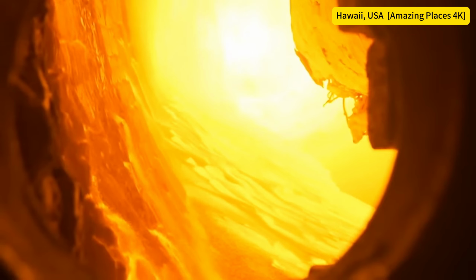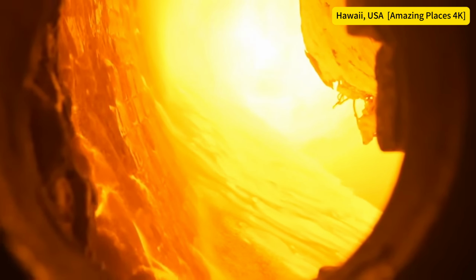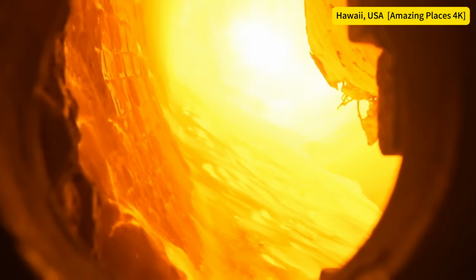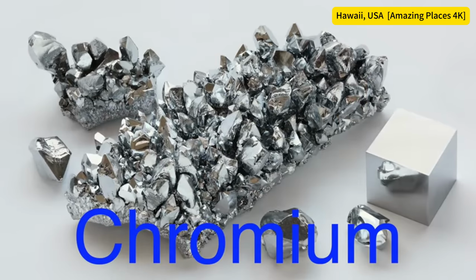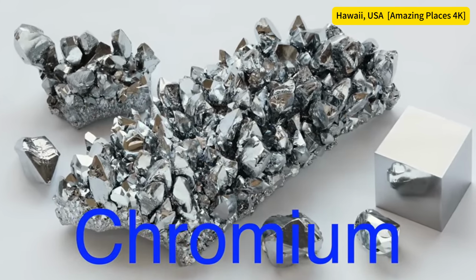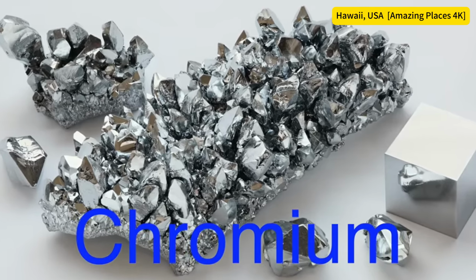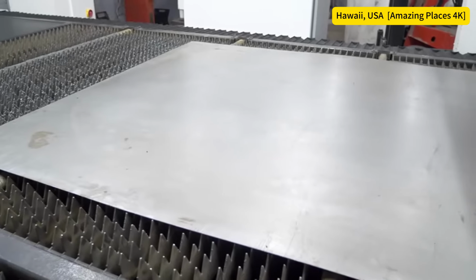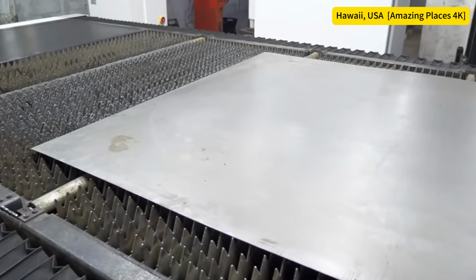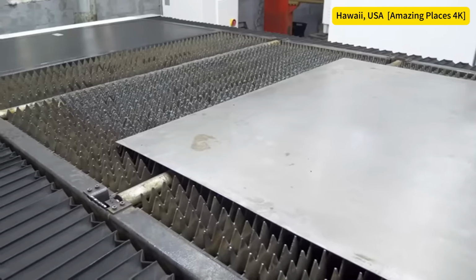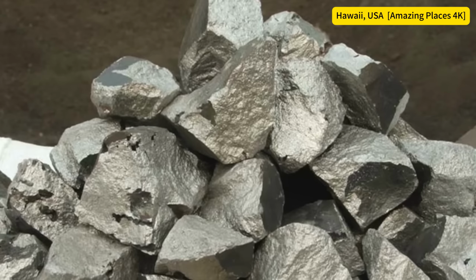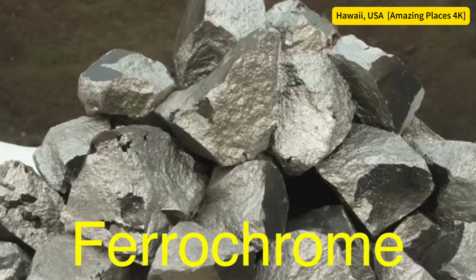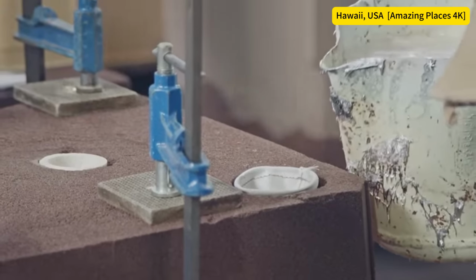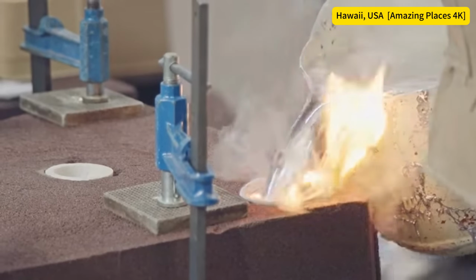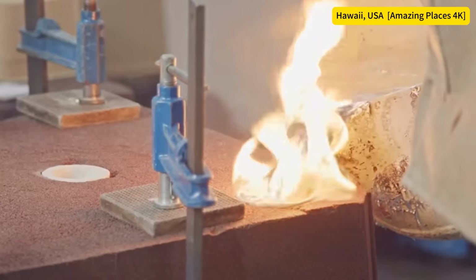However, stainless steel is much more than just iron. Its defining characteristic is its resistance to rust and corrosion, which is achieved by adding specific alloying elements, most notably chromium. Chromium is essential because it reacts with oxygen to form a thin, invisible layer of chromium oxide on the surface of the steel. This oxide layer is what gives stainless steel its stainless property, as it prevents further oxidation and corrosion of the metal beneath. To achieve this, chromium is added to the molten iron in the form of ferrochrome, an alloy of iron and chromium. Typically, stainless steel contains at least 10.5% chromium by weight, although the exact percentage can vary depending on the grade of stainless steel being produced.